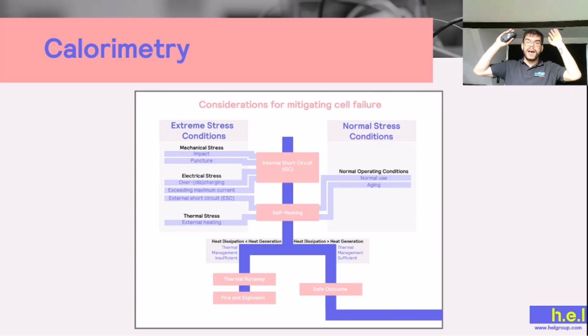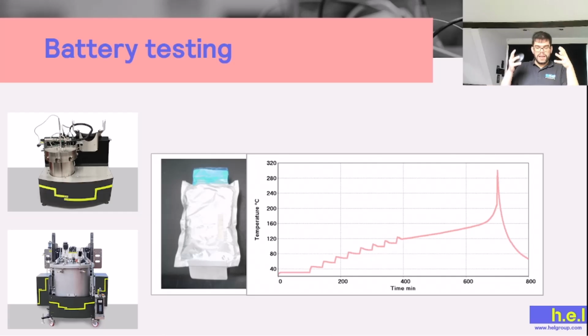And this can result in internal short circuits, but also in self-heating. So evaluating the internal short circuit and the self-heating is fundamental. And there are two potential outcomes of this analysis. One of them, and that's the scenario that we want, is that the heat dissipation in the battery is going to be higher than the heat accumulation. That's going to be a safe outcome, and the battery is ready to be used. But it can also be the opposite, where the heating in the battery is going to be higher than the dissipation of heat, and that can result in thermal runaway reactions and in fires and explosions.